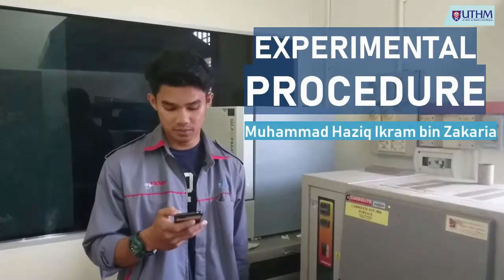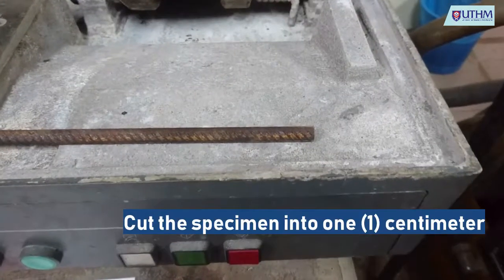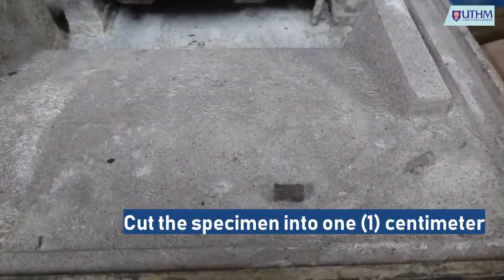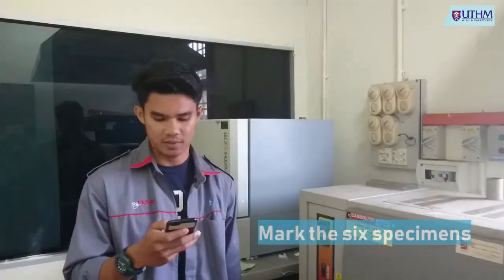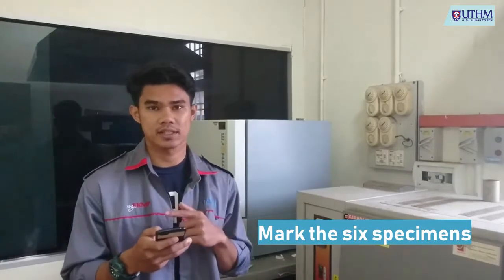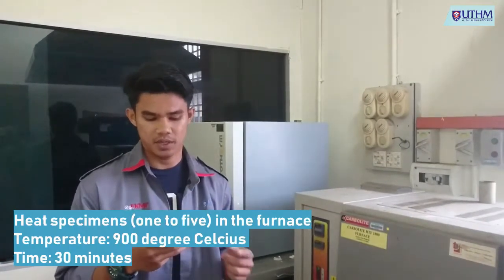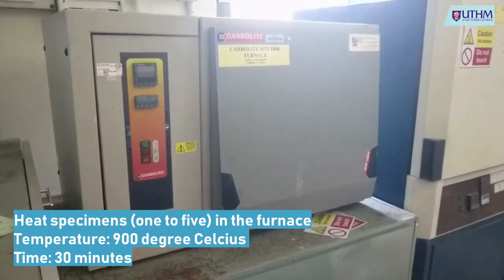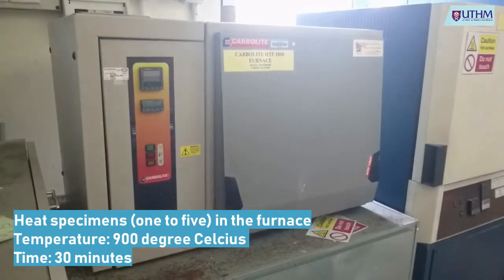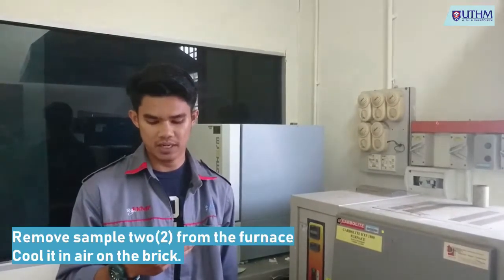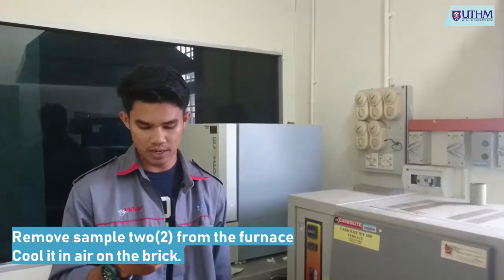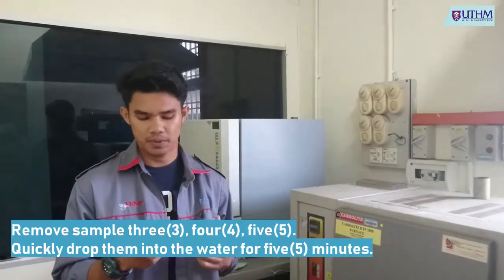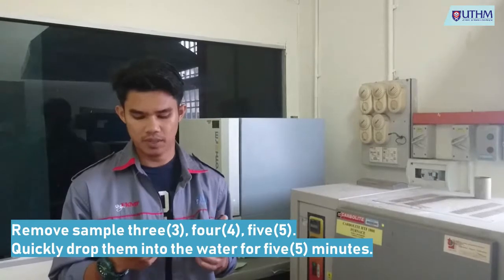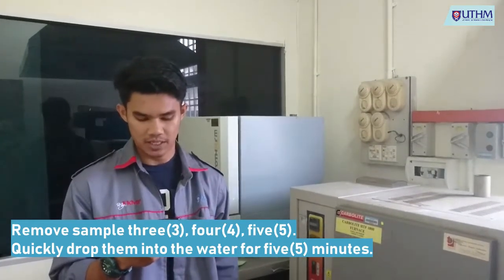For the experimental procedure, first we cut the specimen provided to a size less than 1 cm. Second, mark the specimens 1 until 6. The third, heat specimens number 1 to 5 in a furnace at 900 degrees C for 30 minutes. After 30 minutes, we remove sample 2 from the furnace and cool it in air on the brick. Remove samples 3, 4 and 5 and quickly drop them into water for 5 minutes.